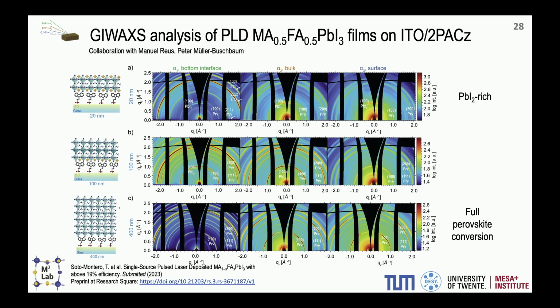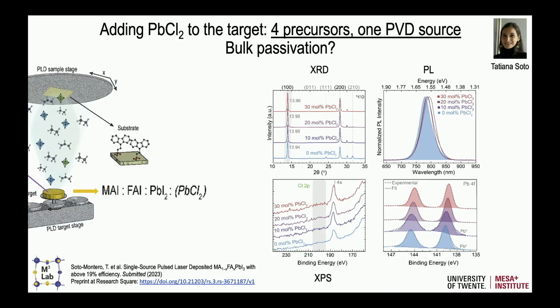So now we understood a bit more how the material grows. And then we can actually say, okay, now we have the material. Can we go for passivation? Because the goal was to show if we can improve the solar cell efficiency. So one of the strategies to do passivation is to add lead chloride. This is something that is also reported in the literature, also for co-evaporation. So in our case, because we work with the target, we said, okay, now we add a fourth precursor in the target.